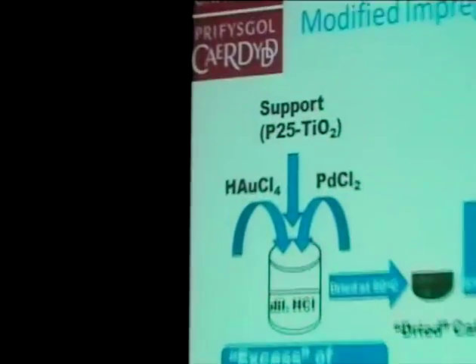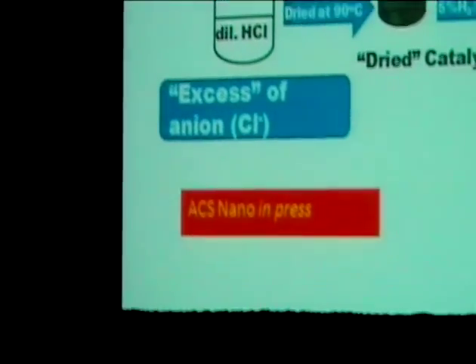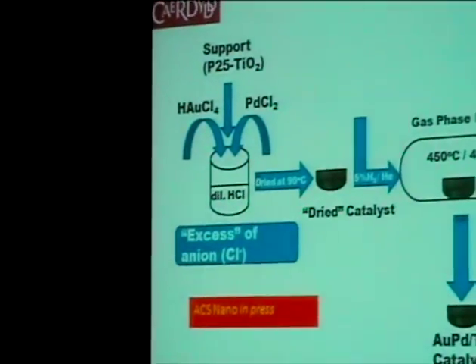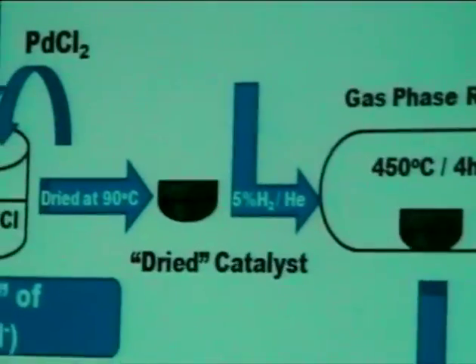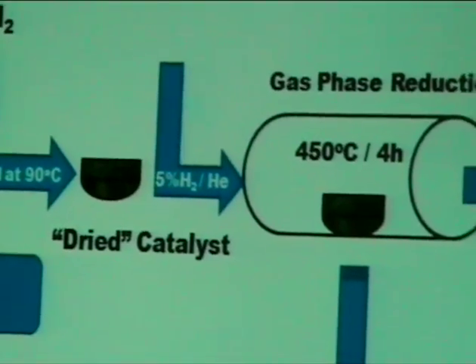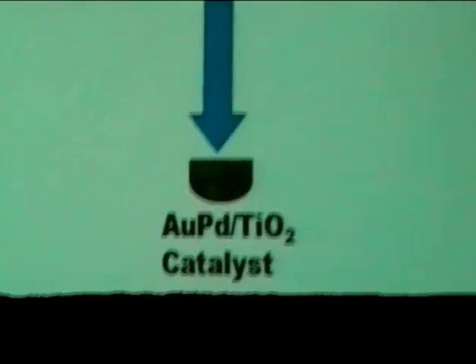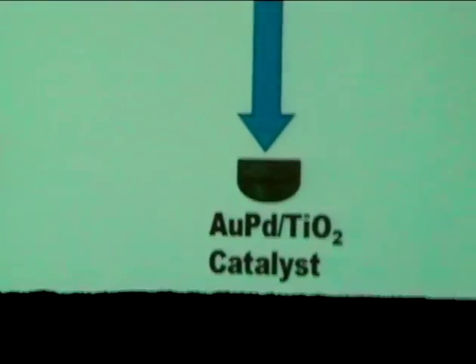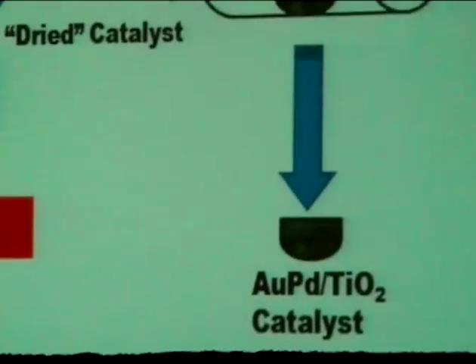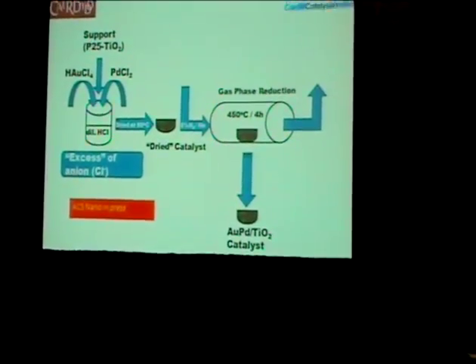To get around this, we've recently published in ACS Nano a new preparation method which we have named our modified impregnation method. This is done using an excess of chloride anions. So we take our palladium chloride and our gold tetrachloroauric acid and our support, and instead of just using an aqueous medium, we use a dilute HCl. We then dry the catalyst off as before, and instead of using an oxidative heat treatment, we also now use a reductive heat treatment, and this helps to remove most of the chloride from the catalyst.